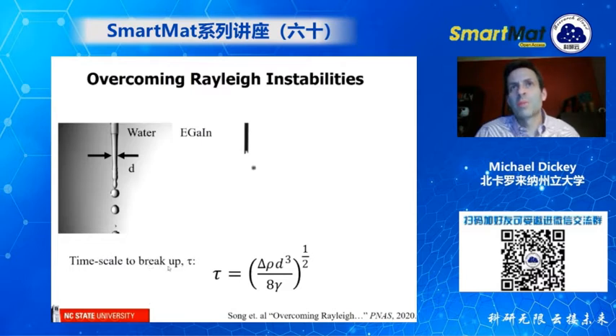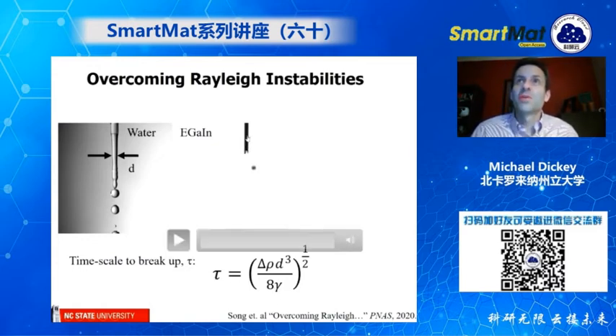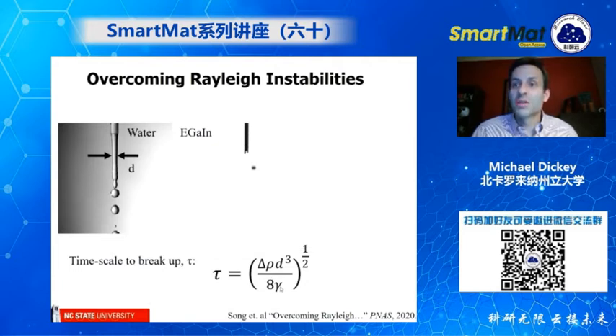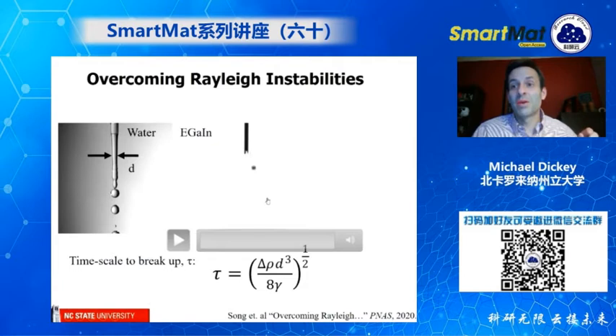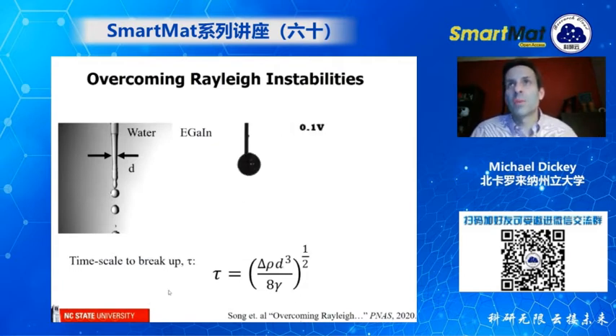The time required for this to happen, this tau term, scales with the diameter of this cylinder to the cubic power. So what that means is if something's really small, like a small stream, it should break up really fast because it should take very little time. And also, if something has a very large surface tension, it should also happen very fast. So we took liquid metal, which remember has the largest surface tension of any liquid, and we pumped it from a 100 micron diameter. So that's a very small D. And we start pumping it, and you'll see it forms droplets.